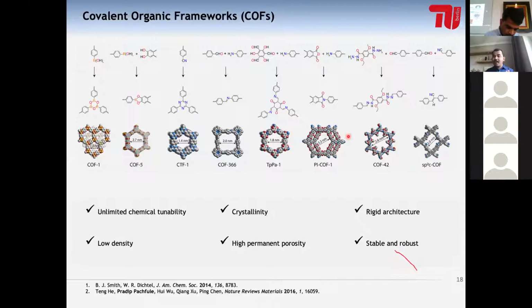They have low density because there are just atoms such as carbon, nitrogen, oxygen, and boron, which form these particular materials. And they have high permanent porosity, with pores such as 2 nanometers, which would give a surface area as high as 5,000 square meters per gram, which is very good for adsorption, hydrogen storage, and so forth. And most importantly, in this case there is not a single bond which can be hydrolyzed using acid or bases, and that's why these materials are very stable as well as robust too.